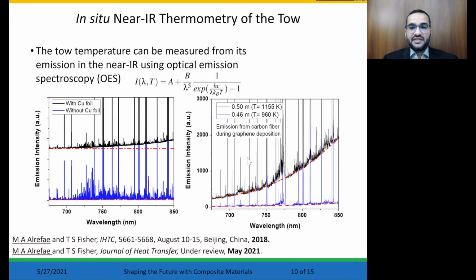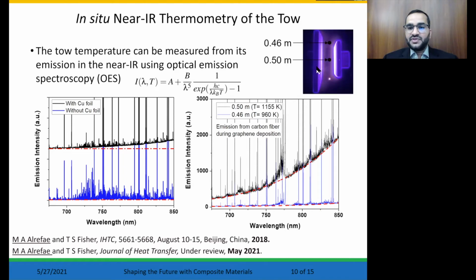The emission spectra in the vicinity of carbon fiber tow during graphene growth are shown here. The emission baseline changes with the tow position in the plasma region as presented in this image. For instance, the temperature in this plasma center line is expected to be high. Therefore, the emission from the tow surface is high. However, the temperature near the plasma edge is expected to be low. Therefore, the emission is minimized. Note that the tow was heated directly by the plasma without applying a supplemental heating, which reduces the production cost.